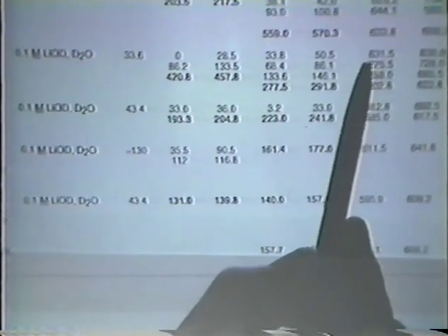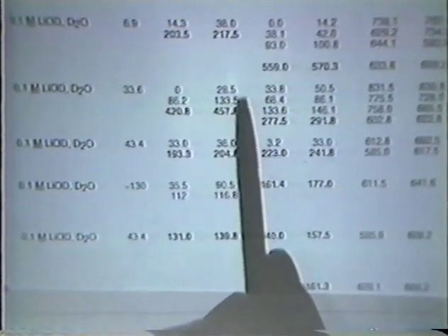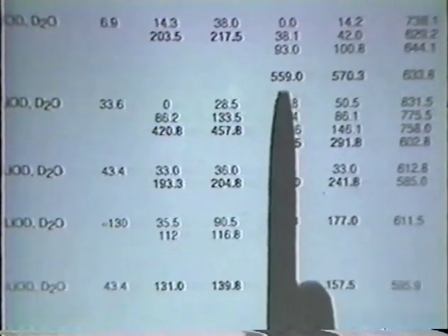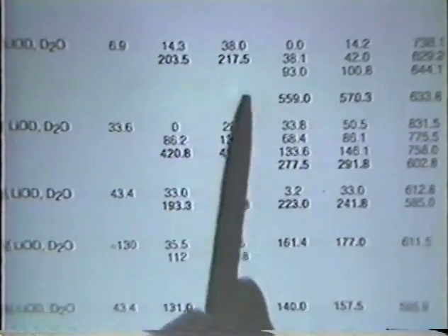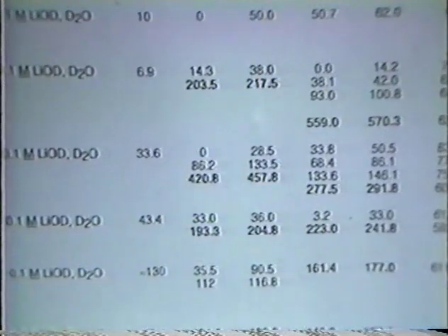Our 2 sigma uncertainty is on the order of 10 to 100 neutrons per cubic centimeter per hour of palladium. We've also then looked at gamma rays produced. We've looked from 20 keV to 30 MeV, both with a high-resolution germanium detector and with a large 15 by 15 by 15 sodium iodide scintillation counter to look out at the 23.8 MeV gamma rays. And again, you see we've run for very long periods of time compared to the activation. We've never seen anything statistically significant, and I'll show you that data also.